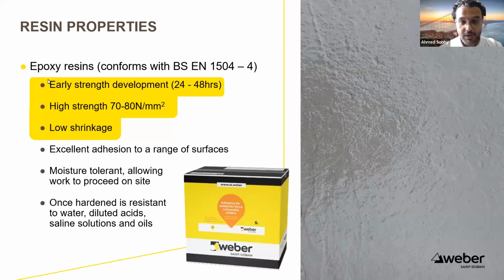That's number one. Number two, when we talk about the most common means of failure, especially right after the application of fiber reinforced polymers, it's usually due to delamination. Delamination could be due to several reasons. One of them is poor application of the material, but also from research and various experiences, the poor mechanical properties of the resins used could play a major factor in delamination of fiber reinforced polymers after application. This is why it's very important for us to give huge significance to the resin type and the properties of the resin that we produce.